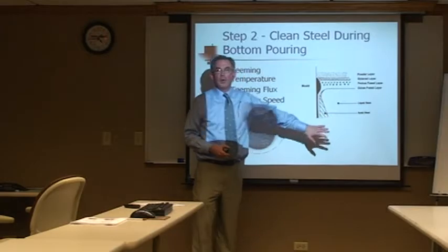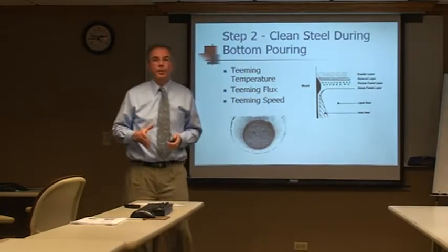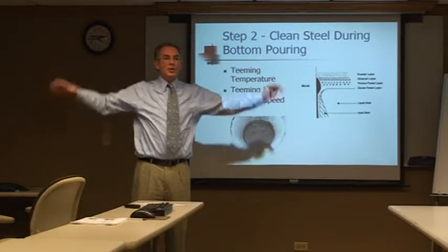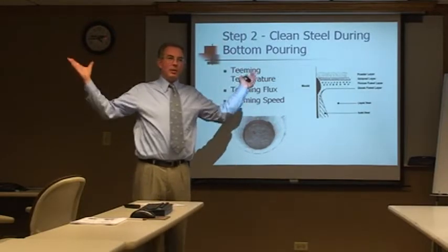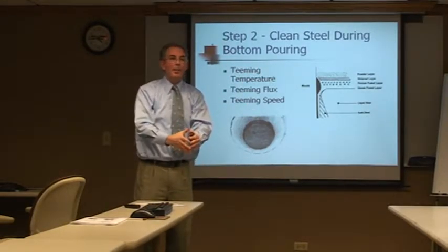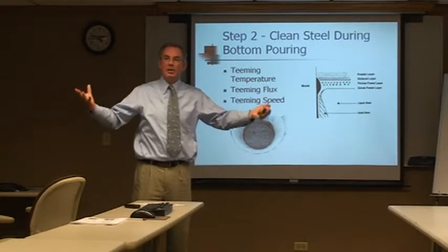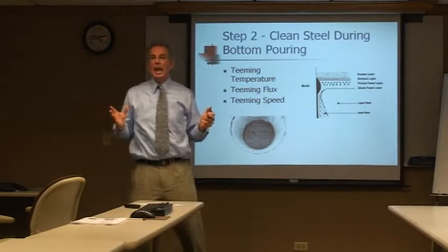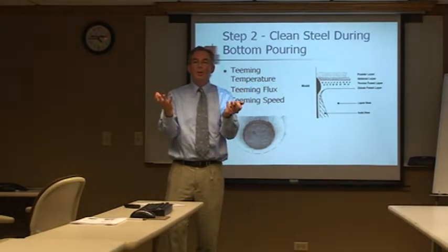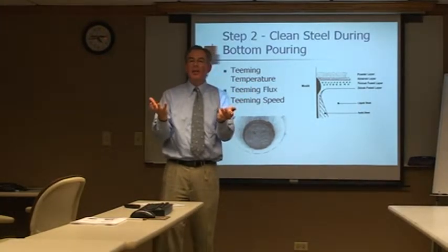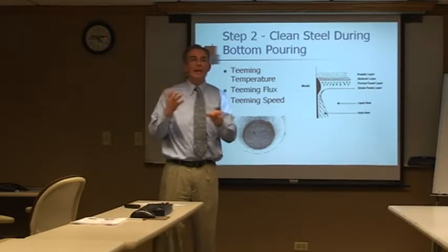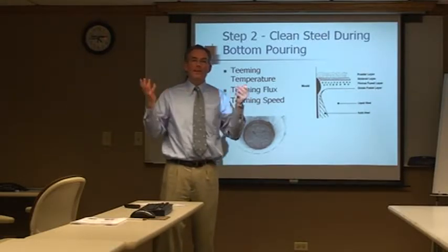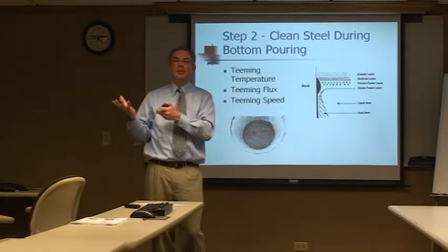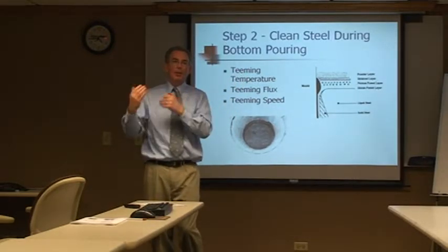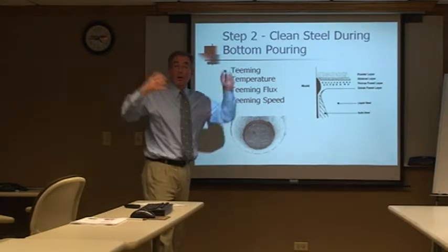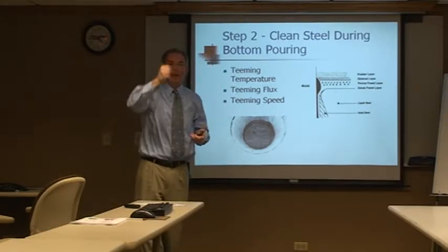So the first thing we want to do, when we pour the steel, you saw the trumpet, what's all around it? There's air all around it. So we've reduced this oxygen content, but what we want to prevent is that steel being exposed to the air. Because when the steel gets exposed to the air, it's going to want to react with the oxygen in the air and reoxidize. And once again, we can't control what comes in contact with the oxygen in the air. So we want to prevent the steel from being exposed to the air. You saw that we're argon shrouding the stream from the ladle into the trumpet.